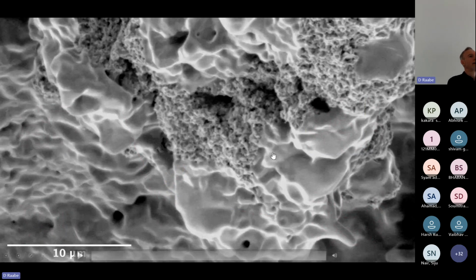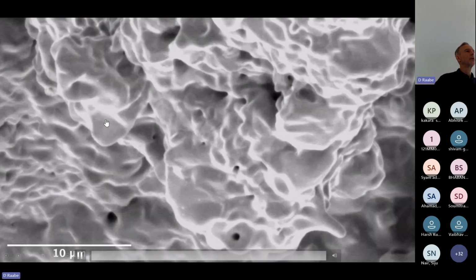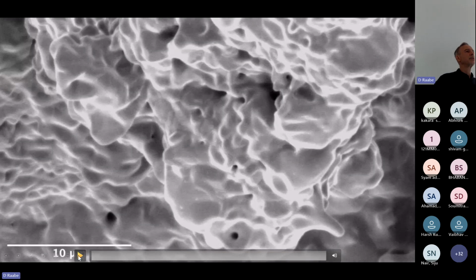And some of that, when I switch now back to experiment, you see also in this little environmental electron microscopy movie that has been taken in a scanning electron microscope where the entire column is flooded by hydrogen. That experiment was done by my colleague, Professor Mark Willinger. And you can see here that you have that rough appearing surface, which is a single crystal wüstite material. And when you expose it now to hydrogen in the electron microscope, and you let that movie run, maybe run it again, you see that the material is overgrown by a relatively flat appearing iron layer, as you can see here.